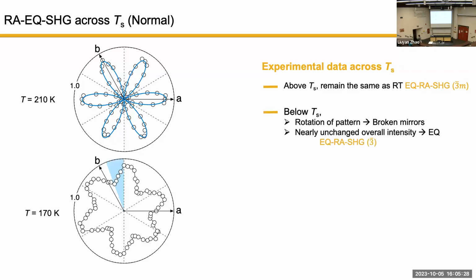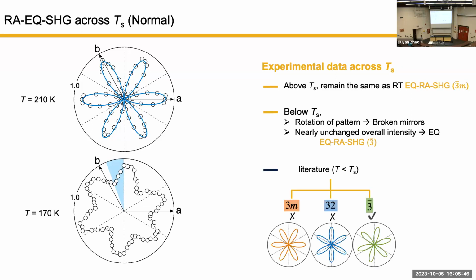Okay. So this rotation away from the dashed line is a strong indication that the original mirror is no longer a symmetry of my data. If it's not a symmetry of my data, it must not be a symmetry existing in the material. Okay, that's the argument here. And then we look into the three candidates that diffraction techniques gave us. So for these three candidates, 3m contains a mirror. If you have a mirror, it's to say that my pattern has to lock to the mirror direction since that's a spatial direction. So our data does not lock, so we rule it out.